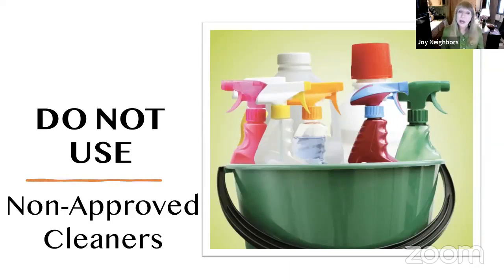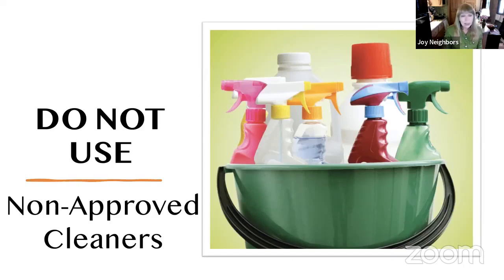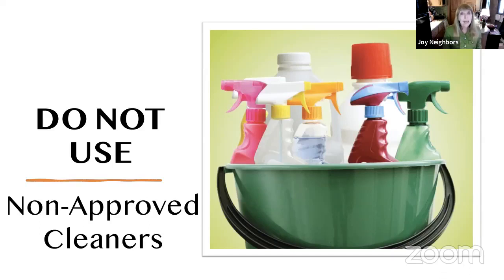Do not use household cleaners or non-approved commercial or outdoor cleaners. Don't use vinegar — I know it's in the cabinet and you can use it at home on your countertops, but don't use it on a gravestone. No bleach, no household cleaners, no commercial spray cleaners, nothing that contains any acid. The first result may be a super-white stone, but the ingredients in those cleaners will eat away at the surface and leave a residue that makes the stone decay even faster.